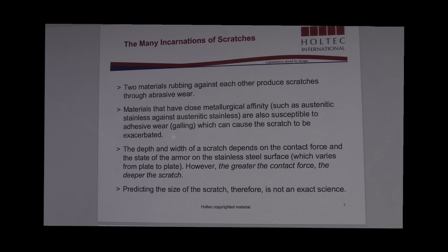What we do know, and can say in general, is that the depth and width of these scratch marks are proportional or related to the contact force, and they are also dependent on, as we say on the slide, the state of armor on the stainless steel. What I mean by the state of armor is that differing plates may have differing chromium oxide layers that act as a barrier, and the indentation hardness, or the Brinell hardness, which is a common measure, may vary from one plate to the other. So that can also influence the depth and width of the scratches. But most certainly, the magnitude of the contact force is a key driver that determines the scratch depth and its size.